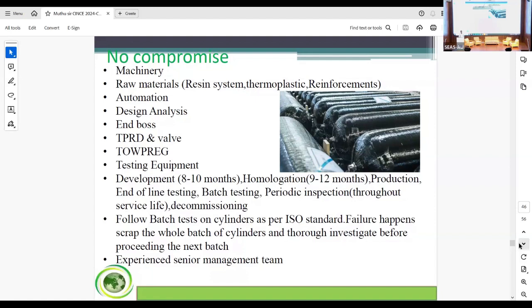So the emboss design and then the main top plug. If you go with the top plug, the cost is 15 to 20% higher of your total cost of the cylinders, but the uniformity will be there, and resin content will be there. So the performance will be there for a long time. If you start, the development takes 8 to 10 months, and homologation 9 to 12 months, then production, end of line testing, batch testing, periodic inspection, decommissioning, everything. These are things you should not compromise. You have to allot certain time for that. If you say I want it in 2 months or 3 months, that is not a way to deal with this project.